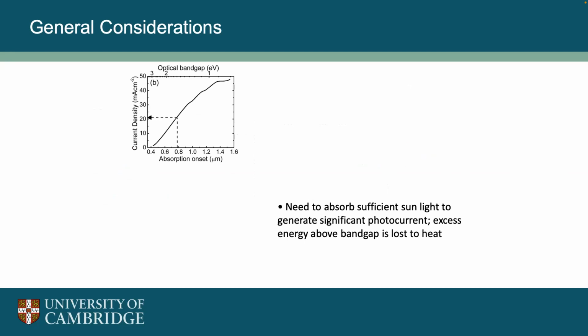So we want this band gap to be as small as possible to be able to absorb as many different energy photons as we can. So one would argue that we should have a small band gap to do that. And so you can think about, this is looking at the current density of a solar cell, and looking at the absorption onset, or in other words, the energy decreasing. And as we decrease the band gap, you can see the photocurrent of the cell goes up. And that's all well and good. We do lose some of the excess energy above the band gap to heat, but that's inevitable.